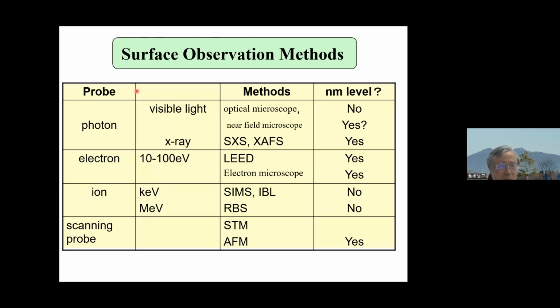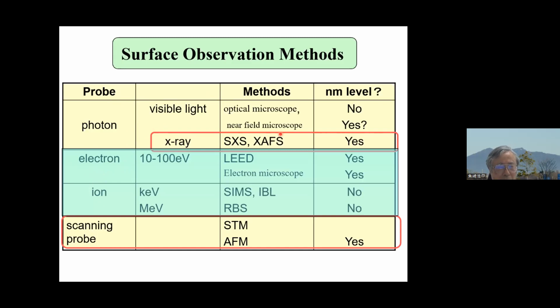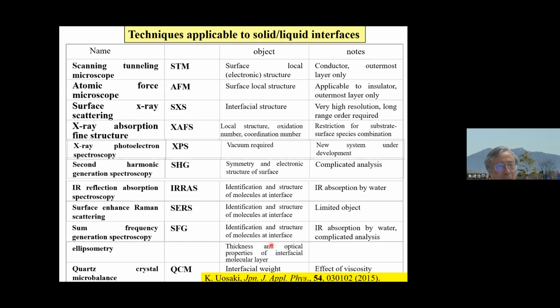For the measurement, there was also a lot of development. For surface observation, you need photons, electrons, ions, or a scanning probe as a probe. In the case of nanostructures or solutions, you cannot use electron or ion probes because they interact so strongly with matter. So X-rays are one of the very important techniques, and of course scanning probe microscopy. They have been developed very nicely in the last several decades. These are techniques applicable to solid-liquid interfaces. These four are for determining the geometric structure: scanning tunneling microscopy, atomic force microscopy, and the X-ray techniques, surface X-ray scattering and X-ray absorption fine structure.